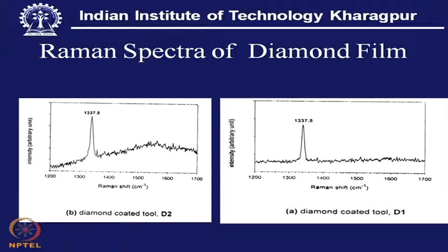Now, there are certain frequencies, given by 1331 to 1337 per centimeter, and with that we expect a sharp peak which corresponds to diamond according to this Raman spectrum. However, if we have some non-diamond phase which is amorphous, then we also expect a certain peak around 1581 per centimeter, that is the Raman shift, and this way we can detect a non-diamond phase. So, we have another coating deposited in another condition. If we keep this picture side by side, then we see that this is a coating free of that non-diamond phase, which would be a weakness of diamond, and here we have this kind of thing.